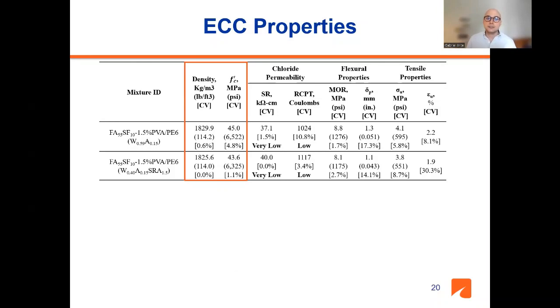The density, as you can see, is very low. These are very light materials. Nonetheless, the compressive strength is sufficient. We're about 6,500 psi. Regarding the permeability of these materials, of course, we want a system that is impervious, so that water cannot continue to penetrate through this cementitious repair and corrode the host metallic pipe.